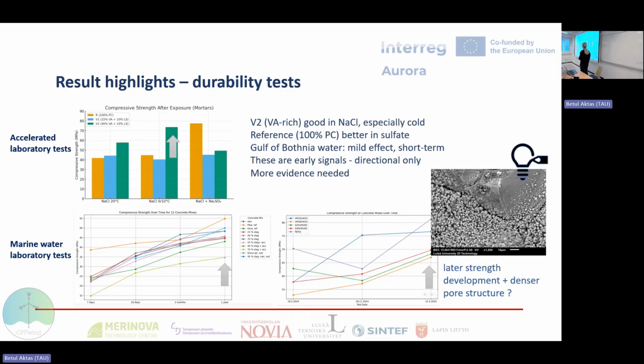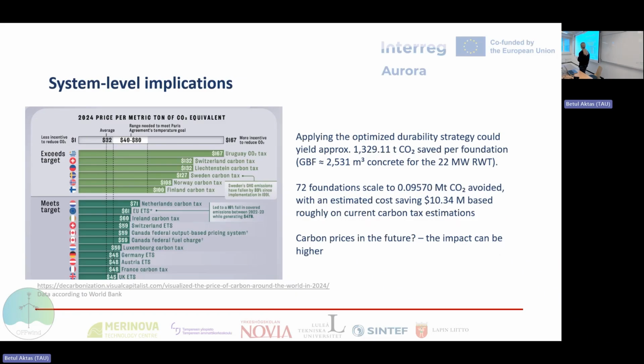With the test with the water from Bothnia, because of the low salinity, the effects were even lower than with accelerated tests. Actually, we observed the increase in strength after 1 year. So we are still looking deeper into the microstructure to understand it better.